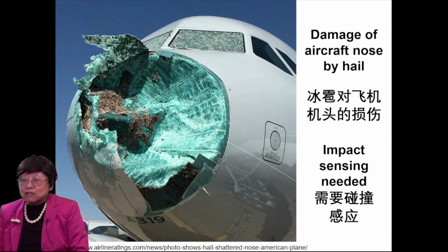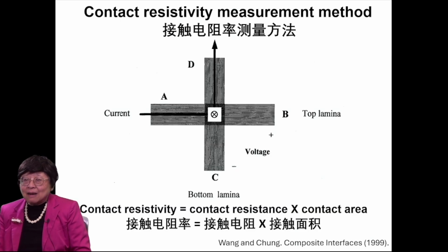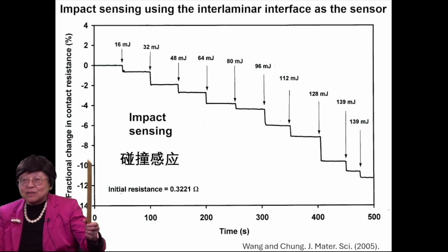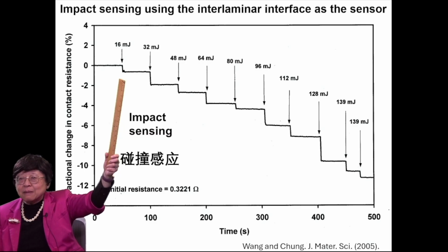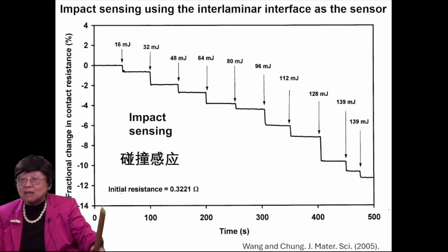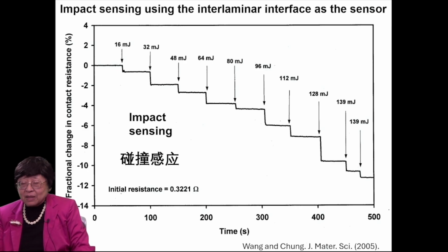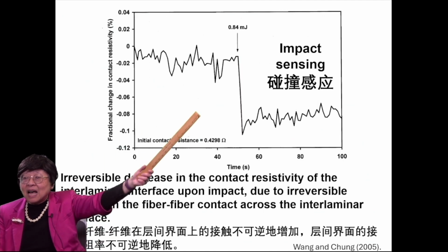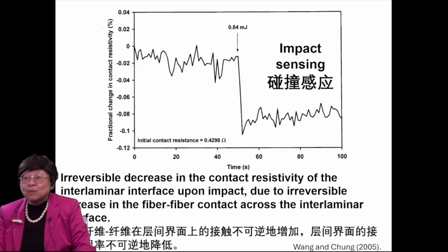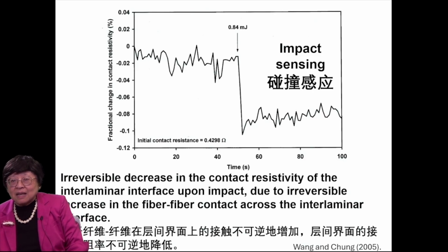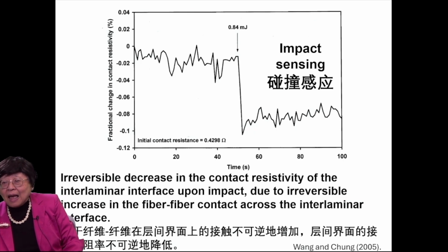Here is damage of aircraft nose by hail, and impact sensing is needed. And the contact resistivity of the interlaminar interface turns out to be very sensitive to impact. And this is the contact resistance during impact at progressively increasing impact energy. And every time one impacts, the contact resistance goes down irreversibly. Even at a tiny impact energy of 0.8 millijoules, we can still see that irreversible decrease in the contact resistivity of that interlaminar interface. And this decrease is because of the irreversible increase in the fiber-fiber contact across the interlaminar interface.